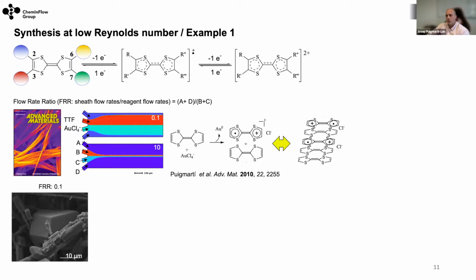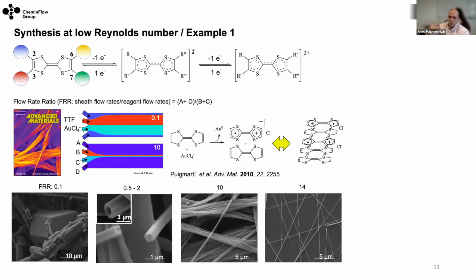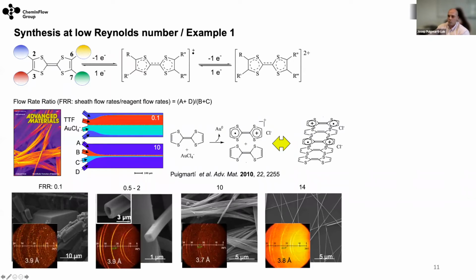So what we observe is that when we work at very low flow rate ratios, we have a mixture of crystals. So they don't have a defined morphology. But as soon as we increase the flow rate ratio, we can even change the crystal habit and obtain nanowires. But most importantly in this work, it was to prove that by changing the flow rate ratio, we were able to change the pi-pi stacking distance of the product.